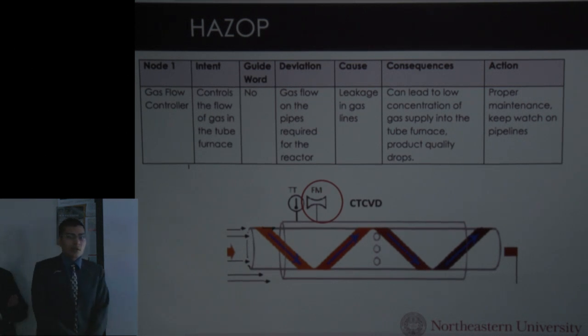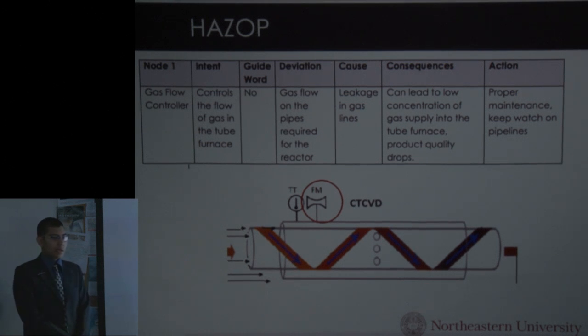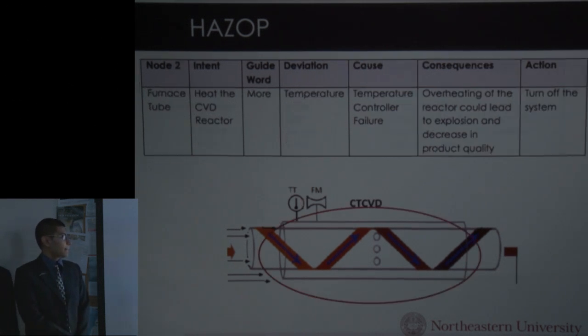And again, based on our process, we discovered two hazardous nodes. The first one is again the gas flow controller. Like I said before, if there are leaks in the pipelines, then improper gas supply concentration goes into the tube furnace. Leaks of gas can cause severe consequences, and the technicians are responsible to make sure this does not occur. Hence, proper maintenance and watch on pipelines is necessary.